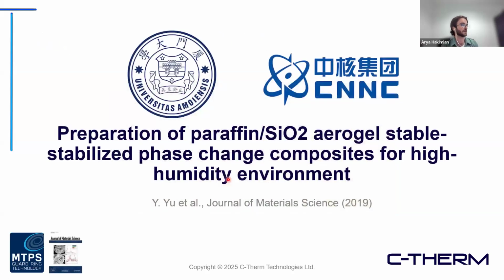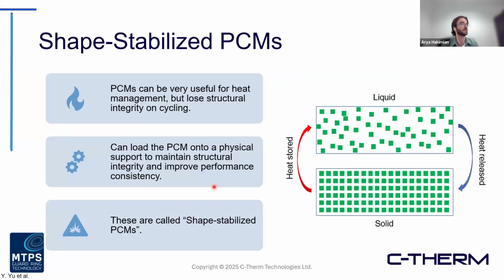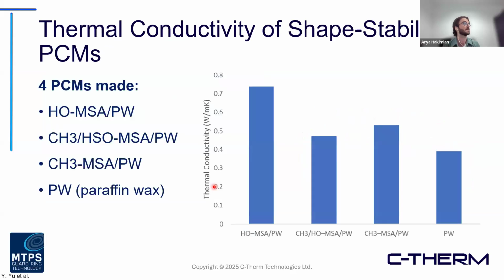Another one here, just wanted to share, this was from 2019, a group looking at PCMs, but specifically shape stabilized phase change materials. They noted again with an aspect of a high humidity environment consideration, but PCMs are oftentimes used in some of these cooling technologies, but some of the challenges is as they cycle, they lose their structural integrity during that liquid to solid phase transition and then back. So what some folks have been investigating is a way to essentially stabilize them using some type of scaffolding or secondary material to help improve on that aspect of things.